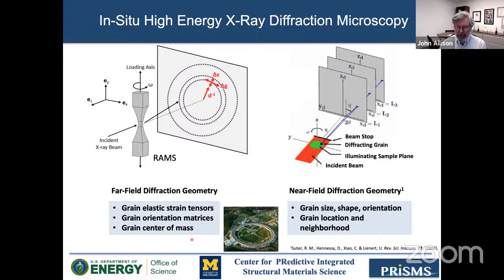I wanted to talk, so I mentioned that it's difficult to quantify twinning using HEDM. And one of our students, Duncan Greeley, took that challenge on, and again, some experiments at Chess, where he did a combination. So there's a technique called RAMS. It's a very tiny sample, about 1 millimeter on a side, loaded, and you can use far field diffraction to look at the elastic strain tensors in each grain and the orientations and the center of mass.